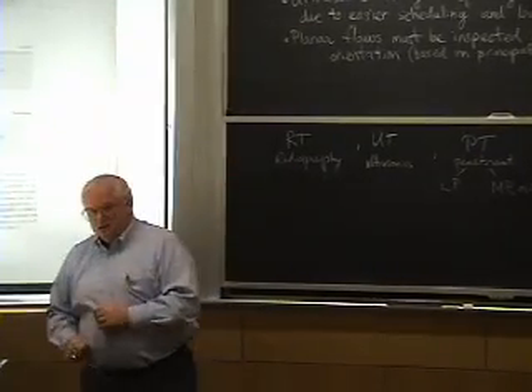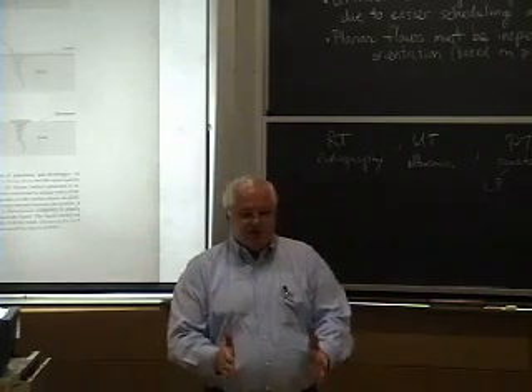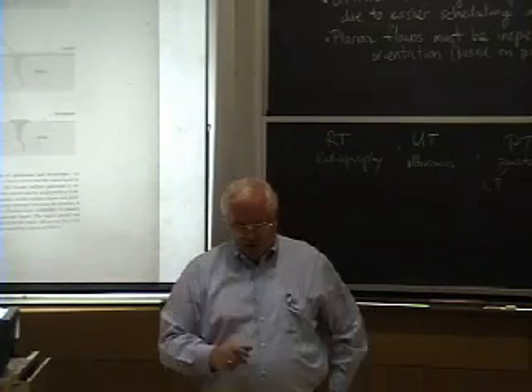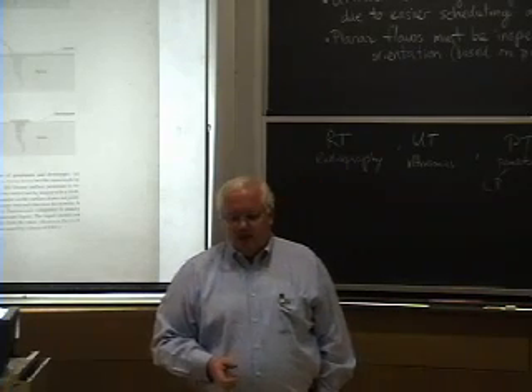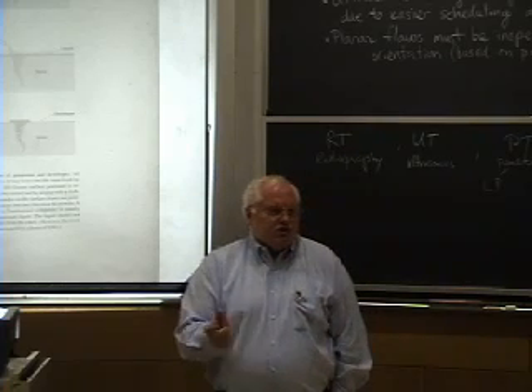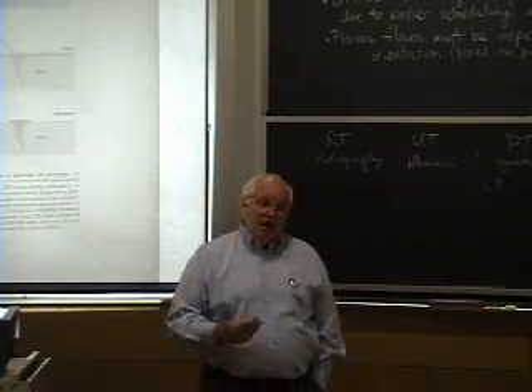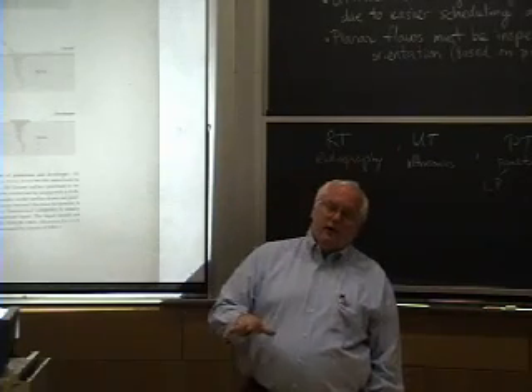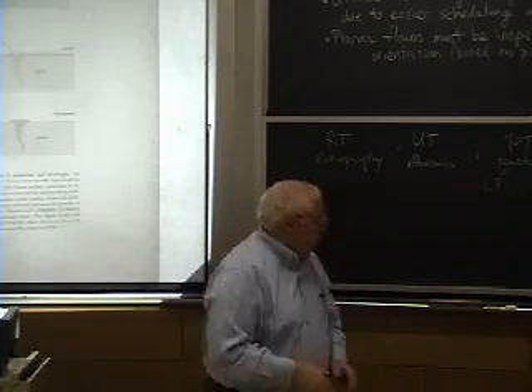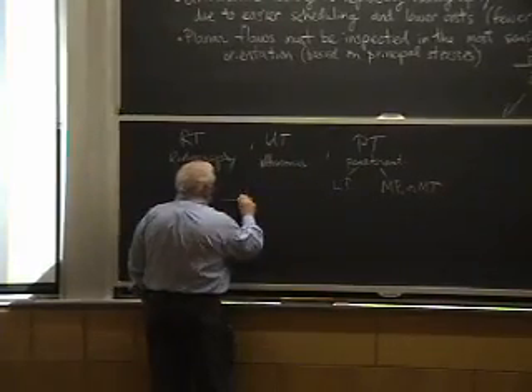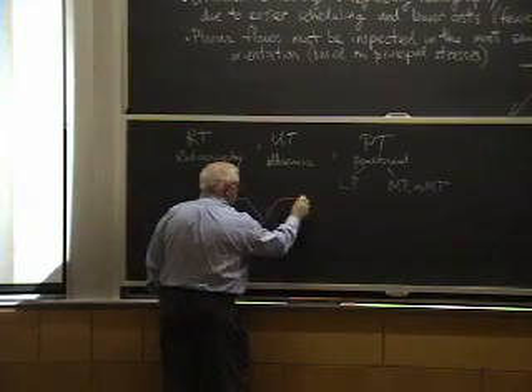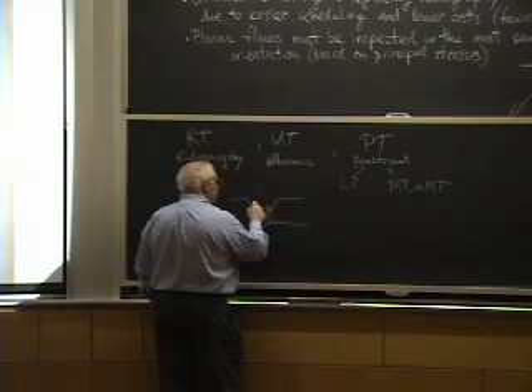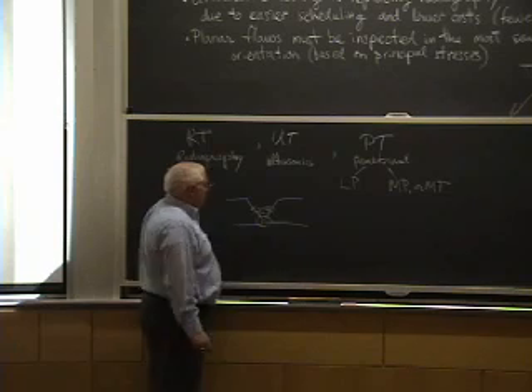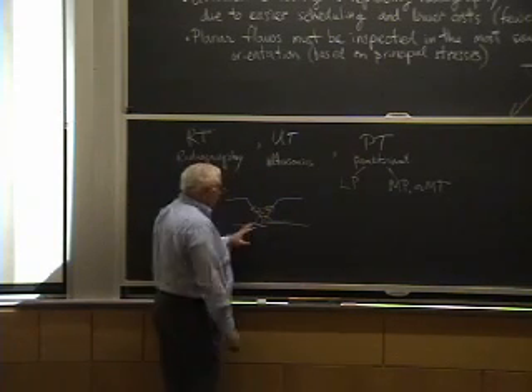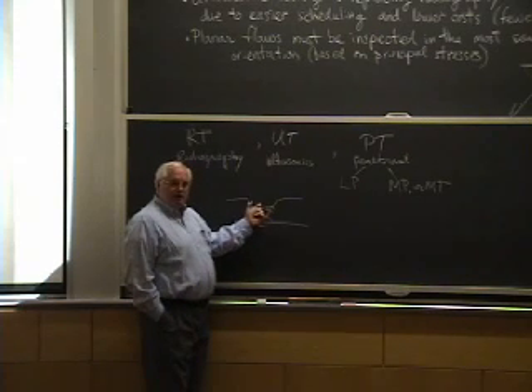Okay? So typically, you can buy a little liquid penetrant testing kit for 60 bucks. It's got half a dozen cans of aerosol, and two or three of those cans might be what they call the cleaner. Well, the cleaner is just a solvent, a degreaser, if you will. You have to be careful to make sure some of these things are safe, because you're going to be testing welds, and you might test a weld that's not complete. If you've got a heavy section weld in some shops, you might build up some weld and actually come in and do a penetrant test before you finish the weld. In which case, you may leave behind some of the residue from one of these three components of the penetrant testing. You better make sure that that stuff is not harmful when you later melt weld metal and electric arc on top of it.